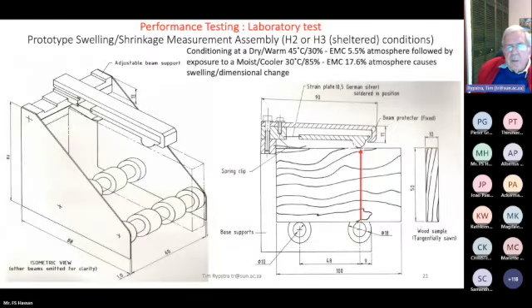As a piece of equipment that can be used under, say, a dry, warm 45 degrees, 30% moisture content of 5.5. And then when all of a sudden the piece of wood is now subjected from that environment to the other, then the dimensional change of that product can be measured, whether it's a natural piece of wood or whether it's wood that has been treated, chemically modified, or even when it's coated, of course, because the coatings have some sort of retarding effect on the moisture pickup, but also once the moisture is inside, it also has a retarding effect when it leaves the wood.